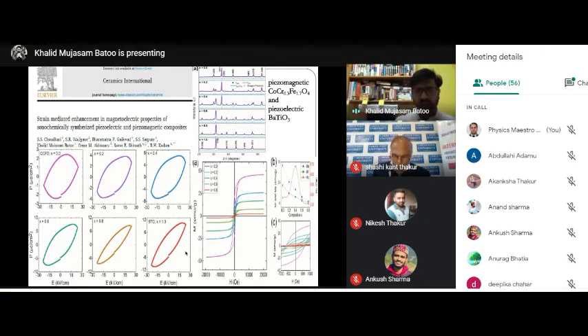What we did in this case is a piezomagnetic combination of two structures. We used cobalt chromium iron oxide, which is piezomagnetic, and doped it with a piezoelectric, barium titanate.